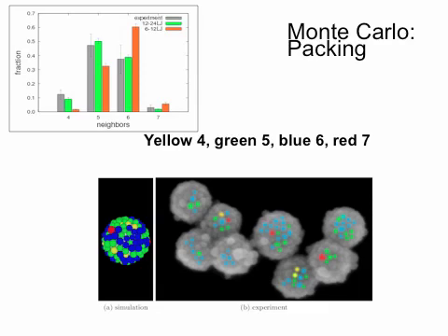So if you do it for monodispersed spheres, the gap in between is roughly 0.15 times the radius of the sphere. So if you want stuff to go in and out in a perfectly flat layer, you know what the space is and how big stuff has to be in order to diffuse through that layer. However, on a curved surface, because of these grain boundary scars, sometimes you have bigger gaps. Yeah, so it's like having a permeable object, and if there's a big hole in it, obviously everything goes in and out there and not through the rest. So it's really important for controlled release to understand this.